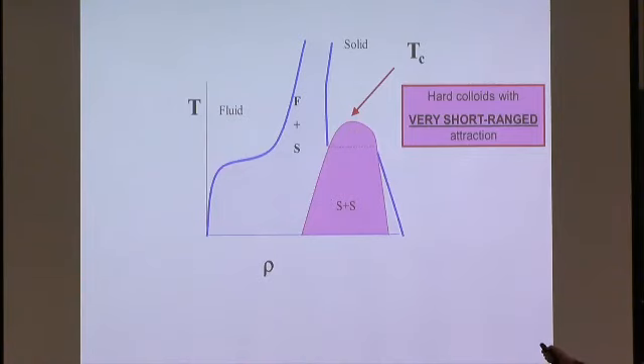And in fact, that coexistence ends in a critical point, much like liquid-vapor, which also have the same symmetry and at some point end in a critical point. So this is a transition between two solid phases that have a critical point, and this actually happens experimentally, not for colloidal systems, at least not shown until now for colloidal systems. It has been shown for certain metals where if you compress them, there's a change in the electronic structure of the core, and you get an isostructural transition between a dense and a less dense crystal phase. So cerium does that, for instance.